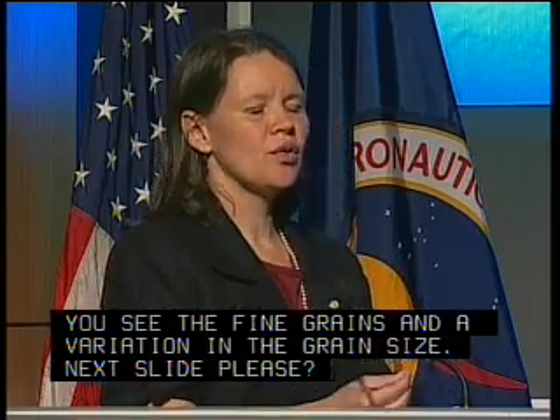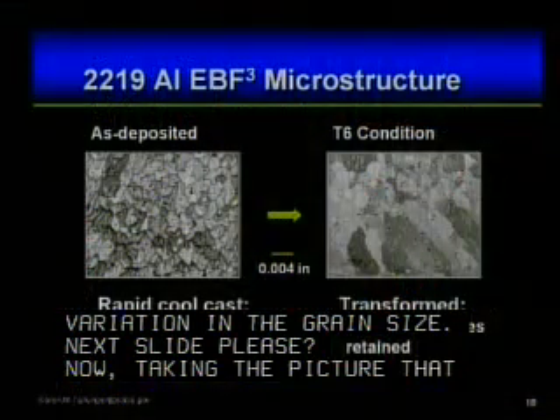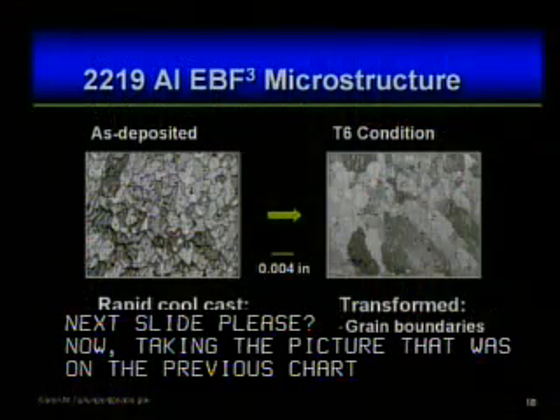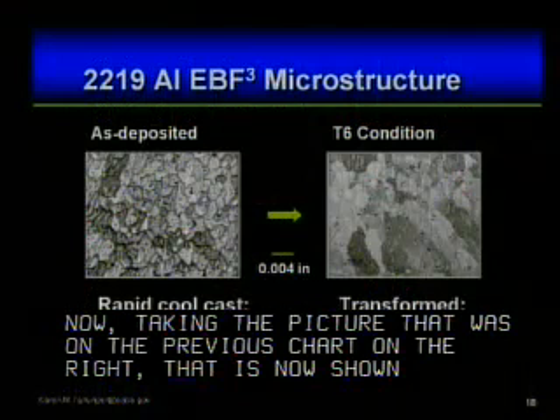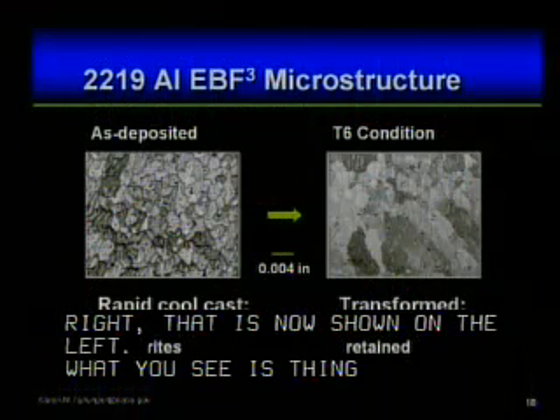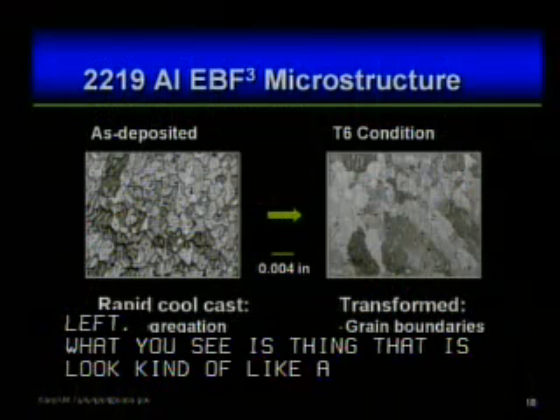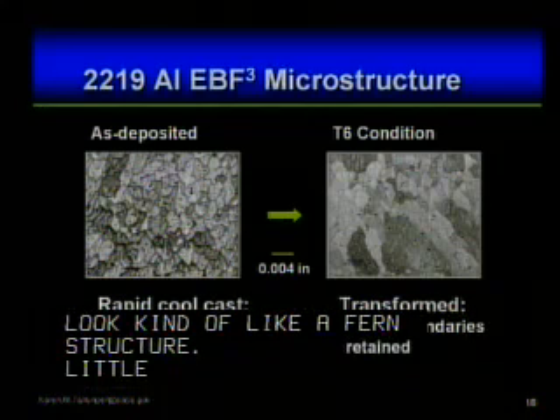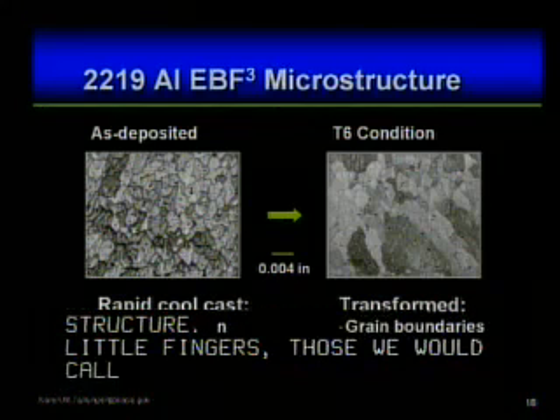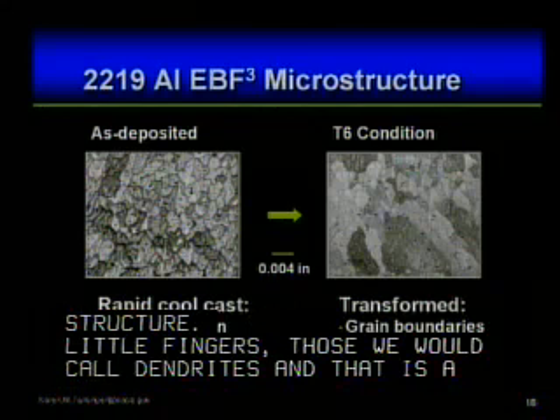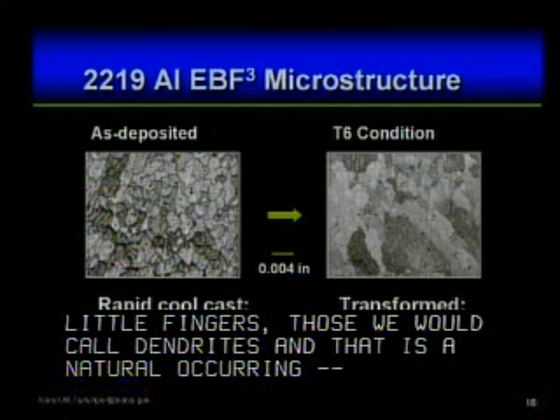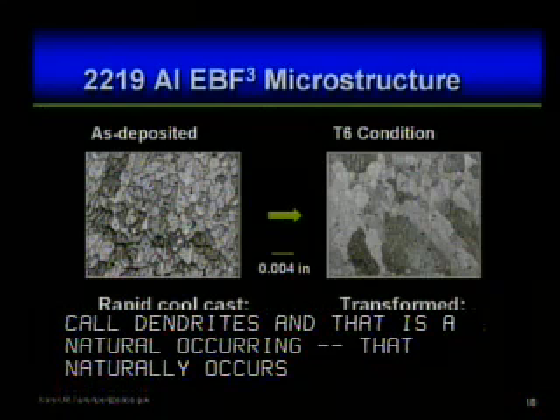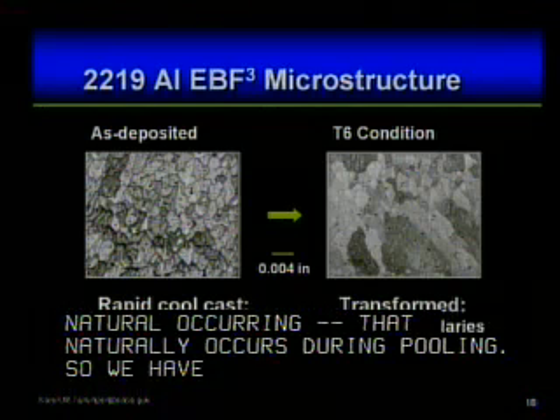Next slide, please. Now, taking the picture that was on the previous chart on the right and looking at it at higher magnification, that's now shown on the left. And what you see is things that look kind of like a fern structure, little fingers. Those we would call dendrites, and that naturally occurs in castings, on cooling. When you take a molten metal and cool it down, that naturally occurs. But we have relatively small grains in the as-fabricated microstructure.